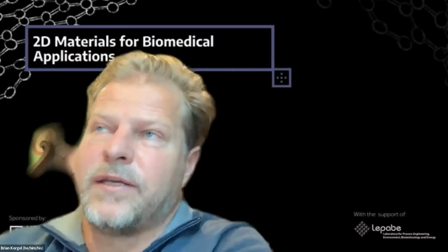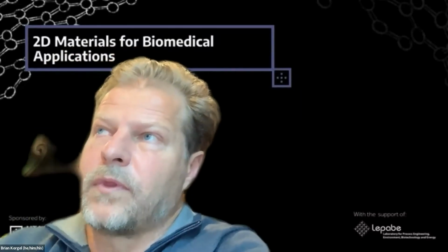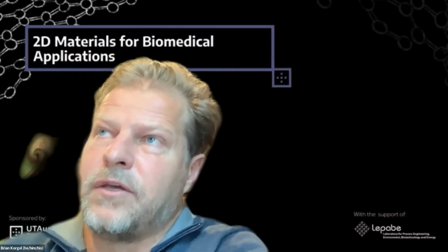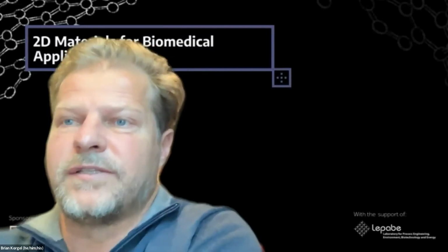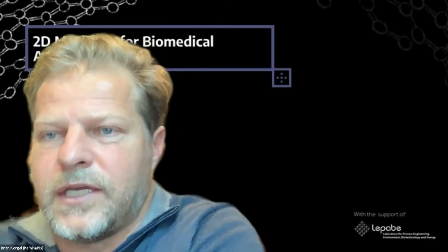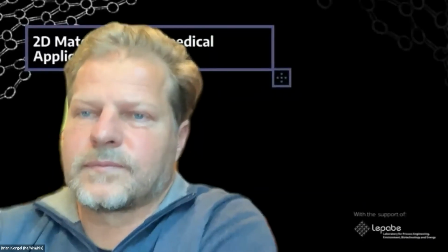What ends up happening, like what I showed, is that the siloxene sheets are very, very unstable under the electron beam when you do TEM, and that will amorphize them. I think what's happening is the electron beam is inducing oxidation. Yeah, we also observe this in the case of orpiment. It's a very beam-sensitive material. If you put the electron beam on it, or even heat the material, it turns from crystalline to amorphous within seconds. So I think this happens with these materials.